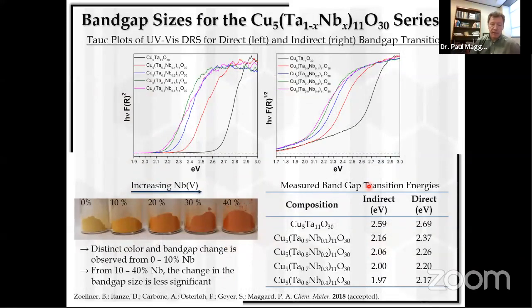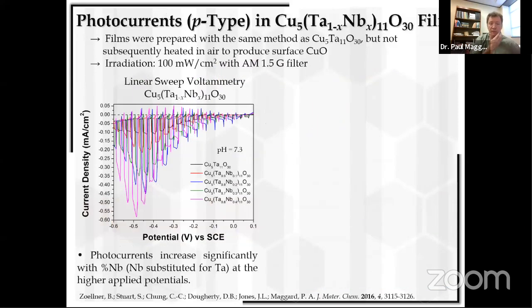So we did this. We made all of these, in this case, by a solid state approach, putting in from 0% to 40% niobium onto that site. And you see that in the UV vis diffuse reflectance, the band edge shifts into the visible, and we're absorbing a large fraction of the visible light now. And we're getting down to a band gap size that is getting nearly ideal, around 2 eV or so, with 40% niobium into it.